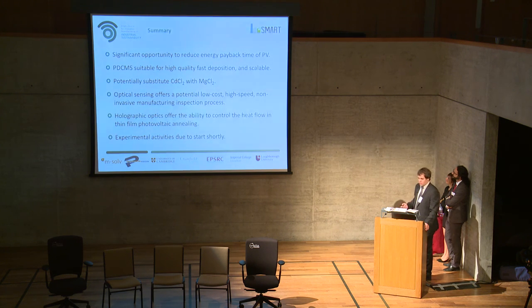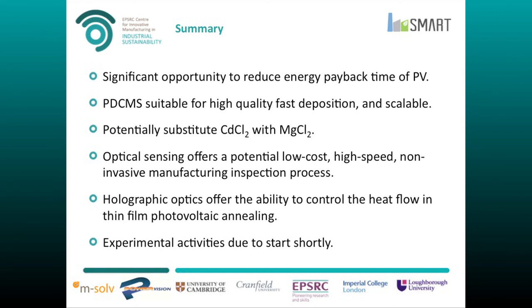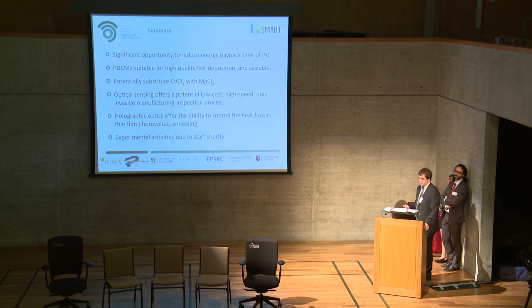So to summarize, we've discovered that there's a significant opportunity to reduce the energy payback time in photovoltaics. We discovered that pulse DC magnetron sputtering is the most suitable for this, for high quality deposition, and it's scalable, so we can do big panels, small panels, experiments, production. We have a potential to reduce the toxicity levels by eliminating cadmium from one of the post-deposition processes and substituting it with magnesium. We can use optical sensing as opposed to expensive electron microscopes, which gives us a low-cost, high-speed manufacturing inspection process. We've discovered that holographic optics give us the ability to control the heat flow in thin film annealing, which allows us to reduce the energy use, and we're due to start experimental activities shortly.